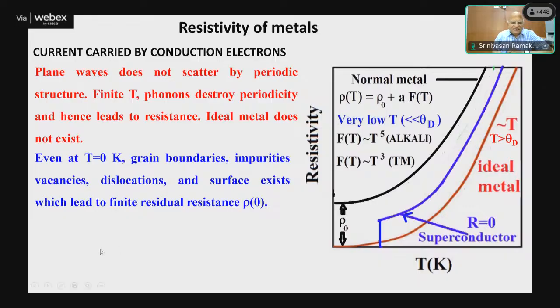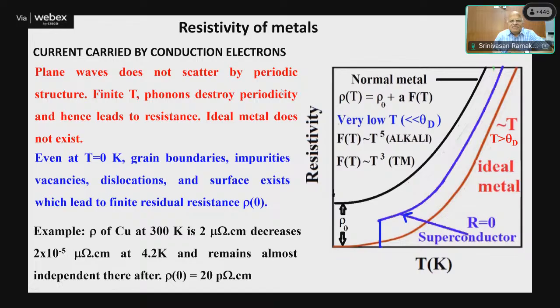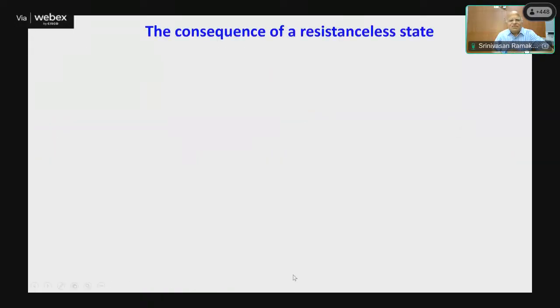So, for instance, let's take the resistivity of copper, which is 2 microohm centimeter at room temperature. It will decrease to about 20 picoohm centimeter at 4.2 K, and it will remain constant because of the disorder in the system. So there is no superconductivity in copper, whereas mercury, as you have seen, does go to a superconducting state at 4 Kelvin.